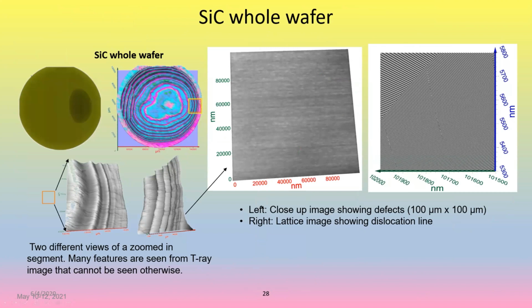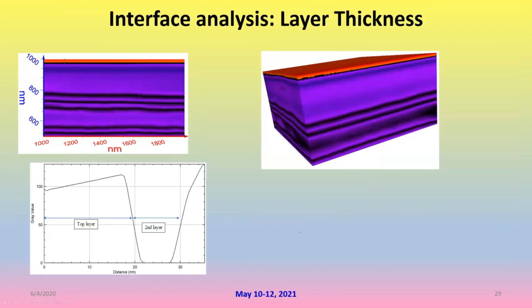So here is another example of a silicon carbide wafer. On the left, as you can see, the image is very monotonic. But when you see under terahertz or T-ray, you see a lot more details that cannot be seen by optics. And also we can see the lattice image here on the upper right. We can calculate the lattice spacing, lattice constants, and determine the polytypes and so on and so forth. Here is a line, what is called a dislocation line, and the nanograin boundaries are visible. We can measure the thicknesses of the epitaxial semiconductor layers.